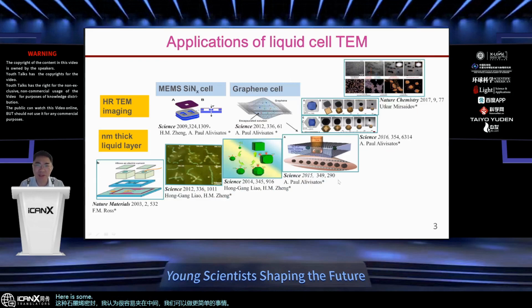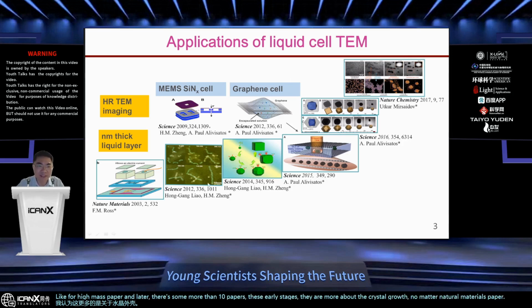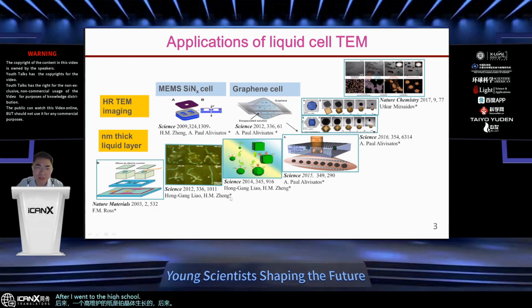Here are some early applications of liquid cell TEM. In the early stage, people mainly worked on the liquid cell for crystal growth, starting with Haimei's paper and followed by more than 10 papers. These early studies were about crystal growth, whether Frances Ross's Nature Materials paper on copper deposition, or Haimei's later paper on platinum crystal growth. Later, in 2012, after I joined Haimei's group, we worked on nanowire growth and shape evolution of nanocrystals, and also the graphene cells, which were also about crystal growth and crystal etching.